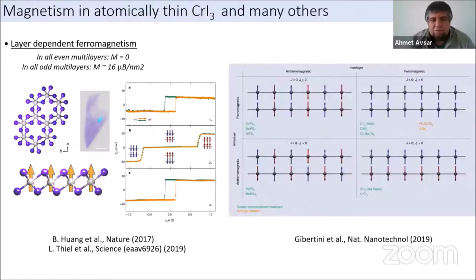Okay, and then soon it was also shown that chromium iodide is not alone. We have very different materials which have this kind of layer-dependent magnetism, but indeed the spin alignments are all different types. So because of the strong competition between the intralayer and interlayer exchange coupling, we have all these sorts of spin alignments. And now we really have material systems which are layer-dependent magnets, and they can have completely different magnetic orientation ordering depending on the material that we choose.